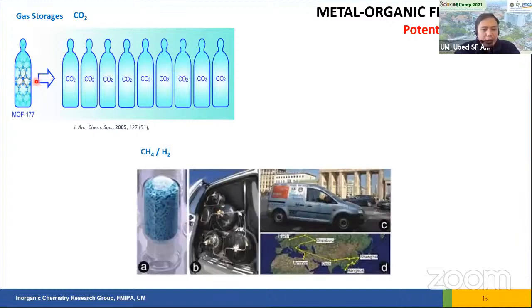And what is it for? We can use this kind of material to store, for example, hydrogen or methane. We can store hydrogen in very high volume with only one gas cylinder. For example, here in Berlin, BASF already uses hydrogen as the fuel of an automobile. So here they are using 5 gas cylinders of hydrogen. If we do not use metal organic frameworks, it means that we need more than 5 cylinders. For example, maybe we need 40 gas cylinders. But with the assistance of metal organic frameworks, we can store a lot of hydrogen or methane in the automobile. And this is very efficient compared to the one without metal organic frameworks in the gas cylinder.